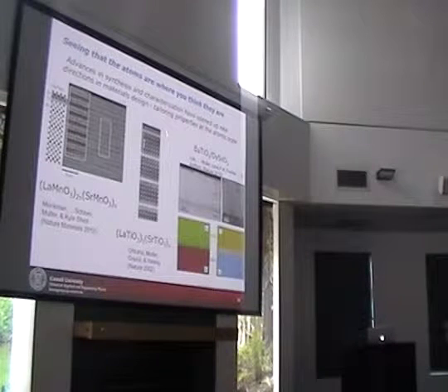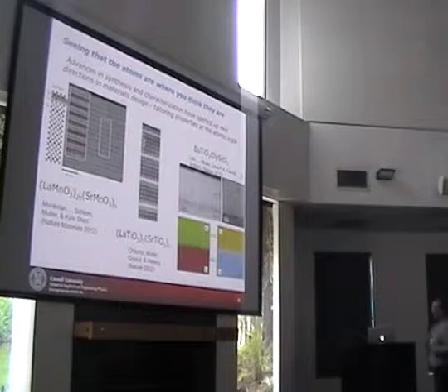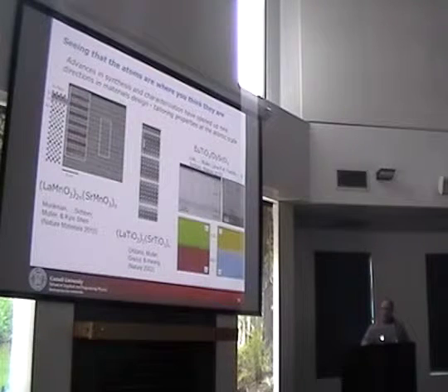This one here, the center one, perhaps 10 years ago or so, really ignited this field of complex oxide interface and interface physics in complex oxides, because this is an example of taking two materials that are bulk, lanthanum titanate and strontium titanate, which are both insulators. And by making this digital superlattice, at the interface between these two insulators, this is a Mott insulator, this is a band insulator, a two-dimensional electron gas emerged. This is a great example of what one can do using these techniques.